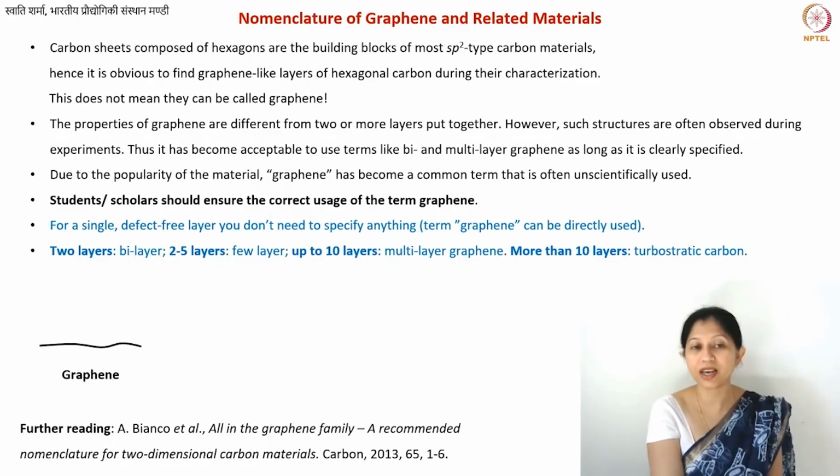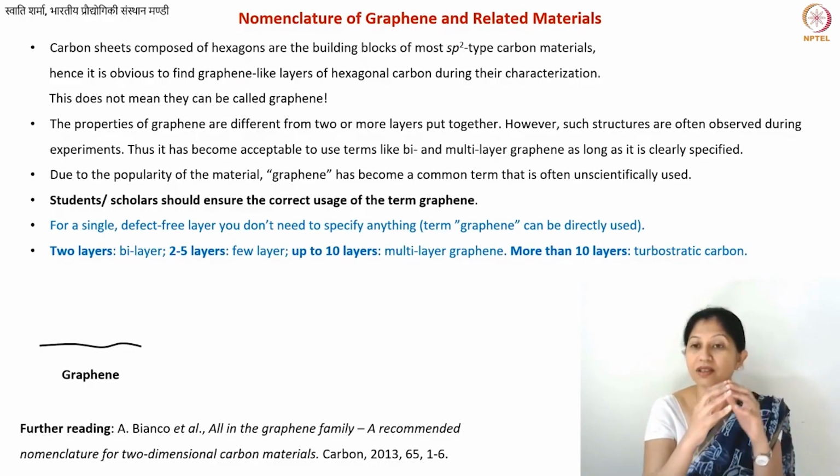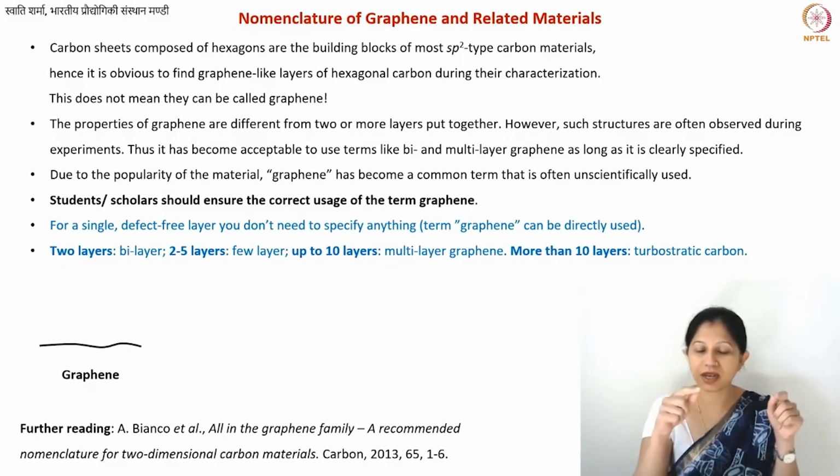The first picture here is what you will call graphene. You will see that it's not a perfectly flat sheet, and there is some waviness. There is some natural waviness in graphene structures, because the bonds are always vibrating. That is not necessarily because of defects. However, defects mean non-6-membered rings, and when you have these non-6-membered rings, you have a stronger curvature. This kind of waviness can also be thermally annealed out. It is sort of a vibrating sheet.